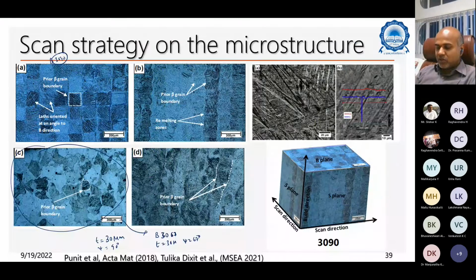Number two, by just varying the scan orientation without changing the layer thickness, you are getting a completely different microstructure. This is actually a more homogeneous, equiaxed microstructure. Okay, this is a very unique microstructure. So this microstructure is more or less similar to what people get in conventional wrought processing, because you're controlling the flow of heat as well as the anisotropy between the layers and so on and so forth.